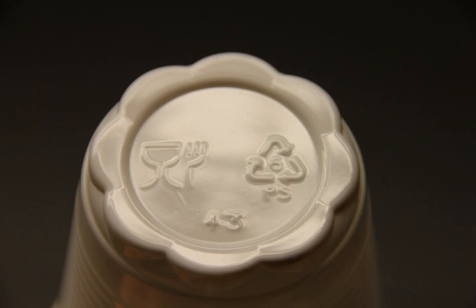Topic. Syndiotactic polystyrene. Ziegler-Natta polymerization can produce an ordered syndiotactic polystyrene with the phenyl groups positioned on alternating sides of the hydrocarbon backbone. This form is highly crystalline with a melting point of 270 degrees Celsius, 518 degrees Fahrenheit. Syndiotactic polystyrene resin is currently produced under the trade name XAREC by Idemitsu Corporation, who use a metallocene catalyst for the polymerization reaction.